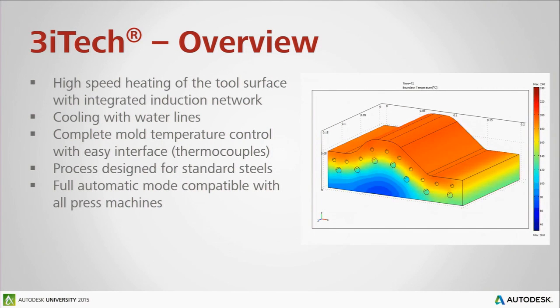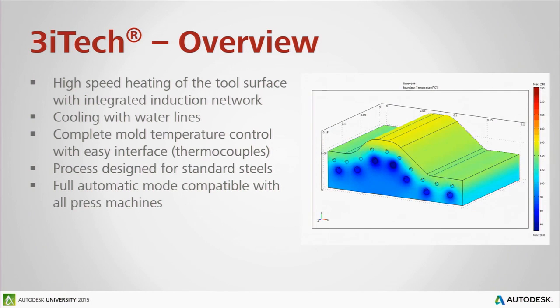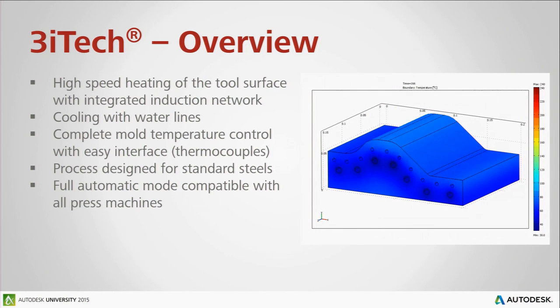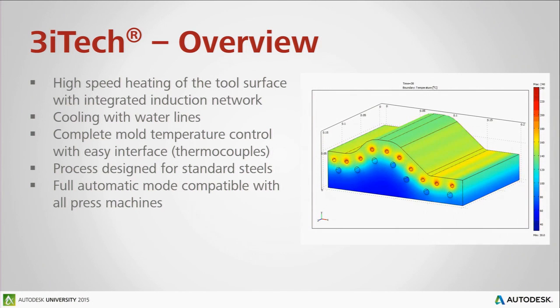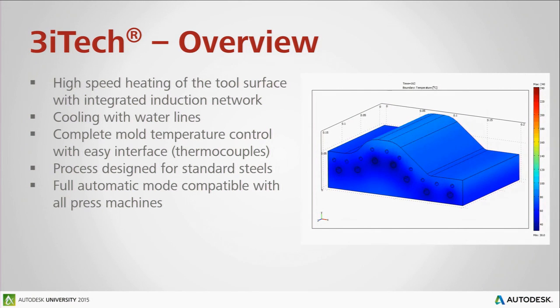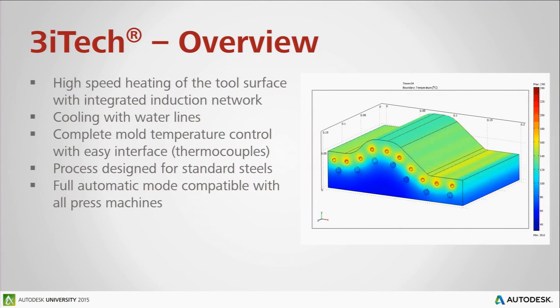So, going back to this, what if we are able to change that temperature with no hassle? Not having to preheat a lot of fluids and push them under pressure through pipes. What if we find a way to heat just enough metal right before the injection so that at the end of that cycle, we can already cool down and get back to our demolding temperature? We looked early on at resistive heating techniques, using the conductivity of carbon fiber or directly of the metal itself. But we found that induction is unbelievably fast.